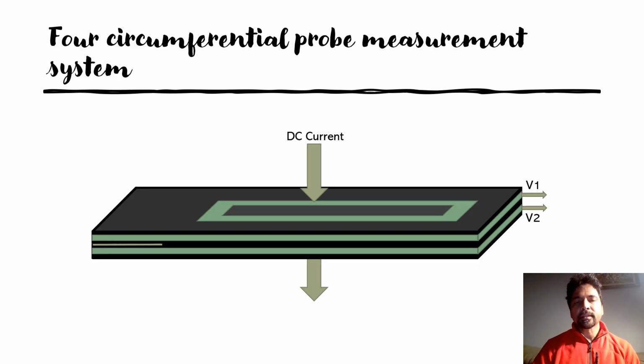The important part of this study is to develop a novel 4 circumferential probe measurement system. This is not available in any standards. We have to think about a better way to send the current as well as to measure the voltage when the crack is propagating. Hence, we employed sending the current through the thickness of the sample as shown in this picture and measuring the voltage along the thickness just above and below the crack as shown in the picture.